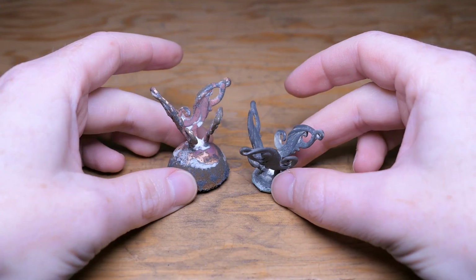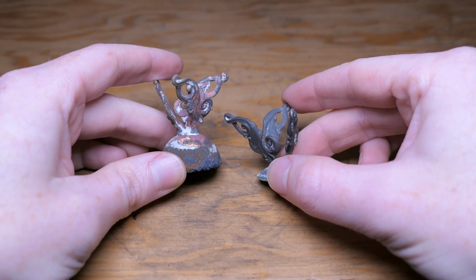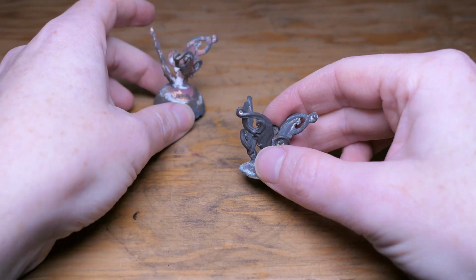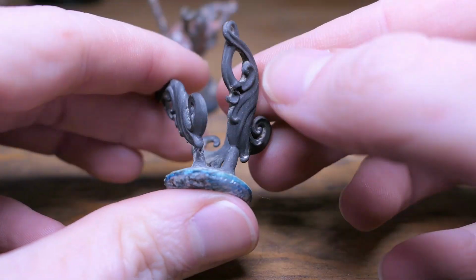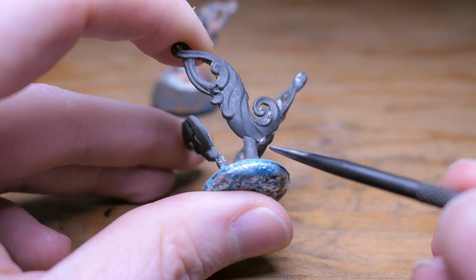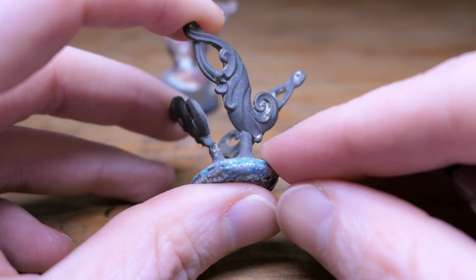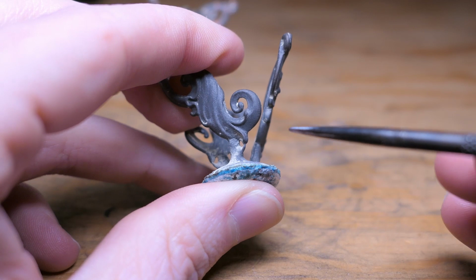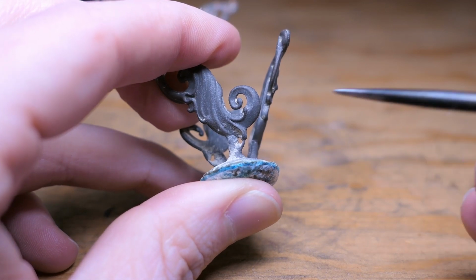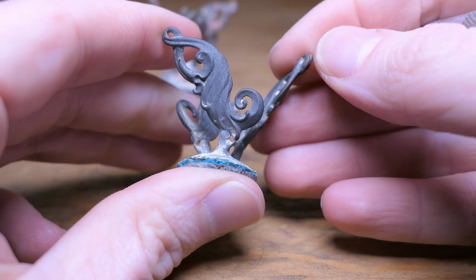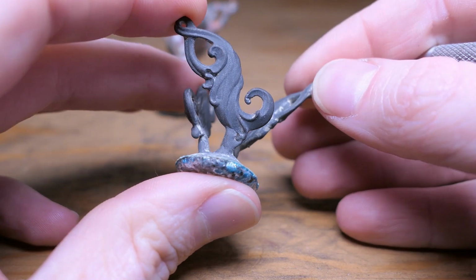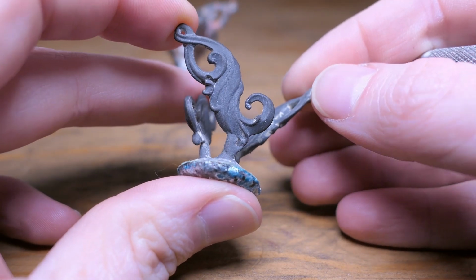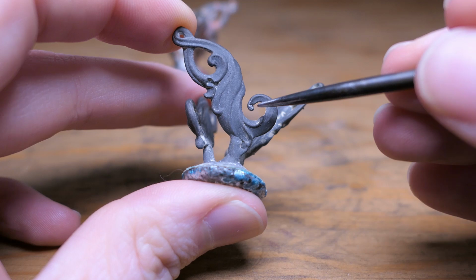And these are the raw castings with most of the investment cleaned off. The silver models came out pretty well with just a few minor blemishes, and you can see removing that gate turned out to not make a difference at all, so it's definitely a good idea to remove that prior to casting. One of the small spirals didn't really fill in completely, which I'm sure is due to poor technique on my part.